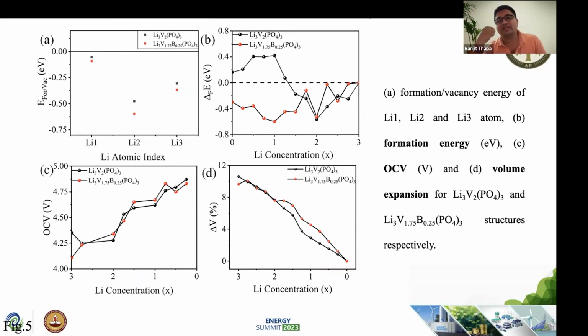So can we do it in such a way? When we bring out all these three lithium, the structure becomes very unstable, because you can see this black curve, after taking out some lithium, 1.8, it goes positive because the structure becomes unstable. So we have put boron as one of the components in place of vanadium. Then we have shown that the structure is stable, even if you take out more than 2 lithium per compound, per lithium vanadium phosphate formula unit, then it is more stable.